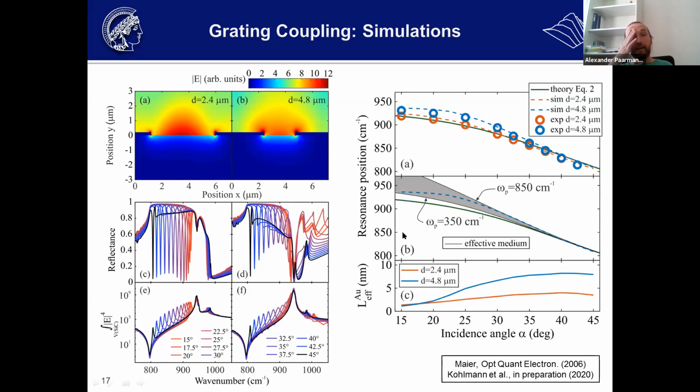All right. One interesting aspect that we also observed here, and that to some people in the nanophotonics community might not be surprising, but we're still learning, so for us it was a little bit surprising, is that the dispersions were actually not exactly the same. On top of this, we saw that the wider gold bars have a somewhat blue shifted dispersion. So you see this offset between the red and the blue.